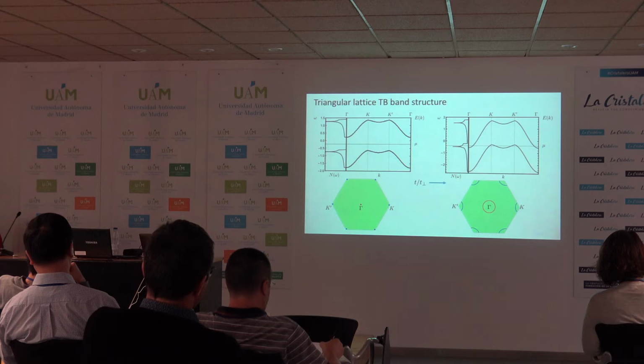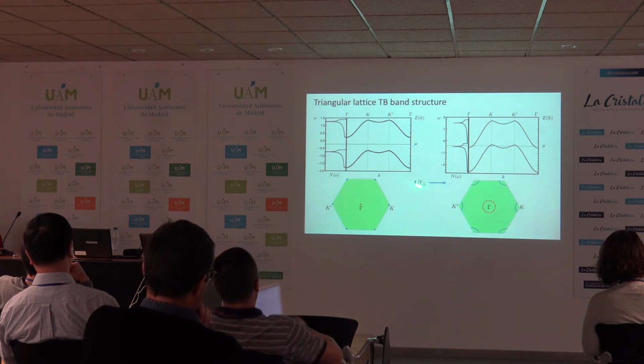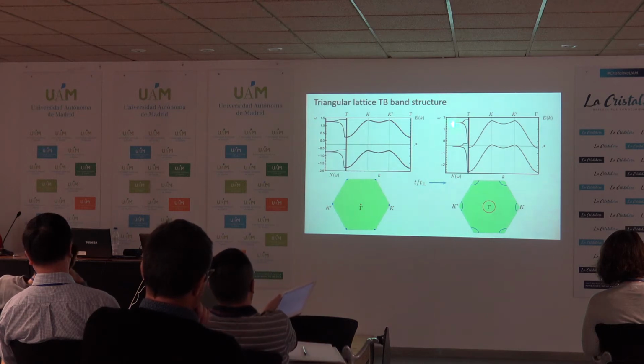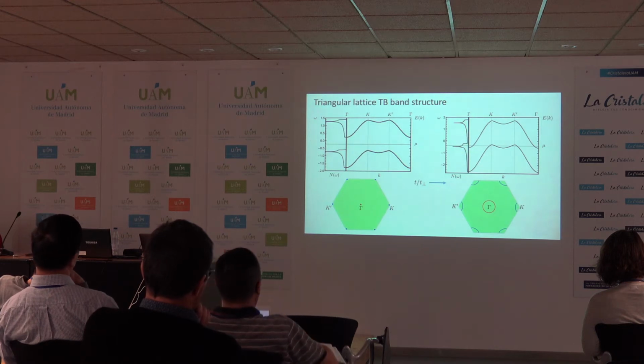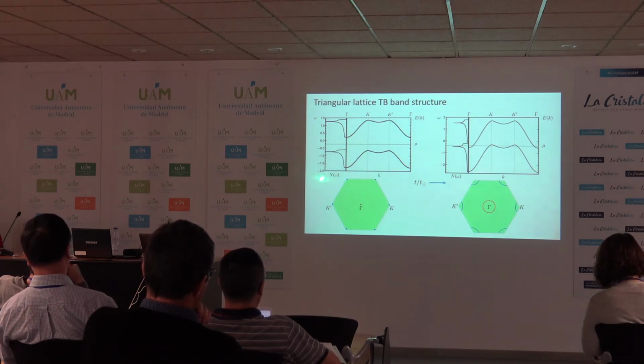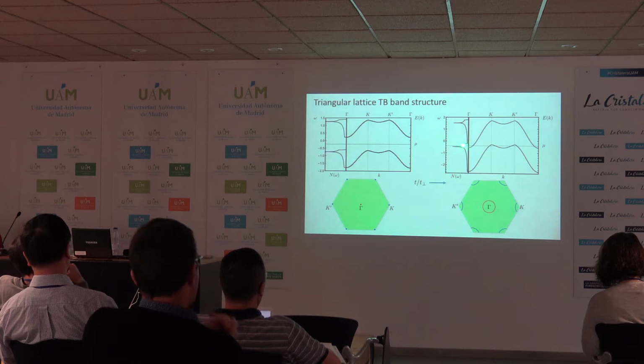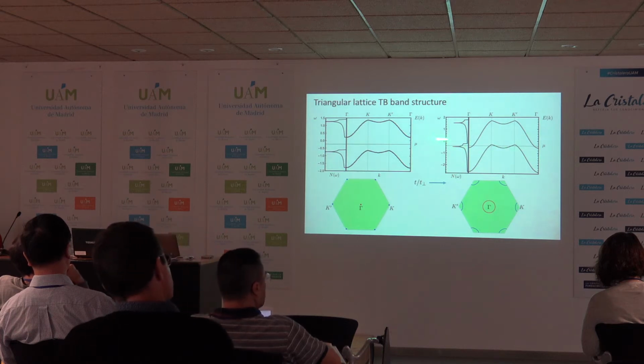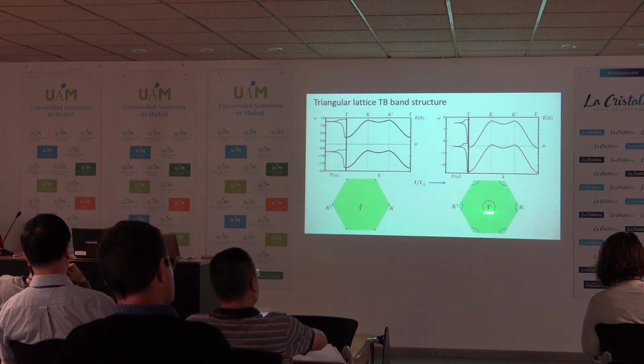Okay, so here's the band structure. This is at a small value of hopping within the layer. So in a way, little t controls the bandwidth of these bands, and t perp controls the separation between the 2 bands. So at small values of t, I basically have a band insulator. And at greater than a certain critical value, you can see now I get states around the chemical potential, and you go into a metal with these pockets.